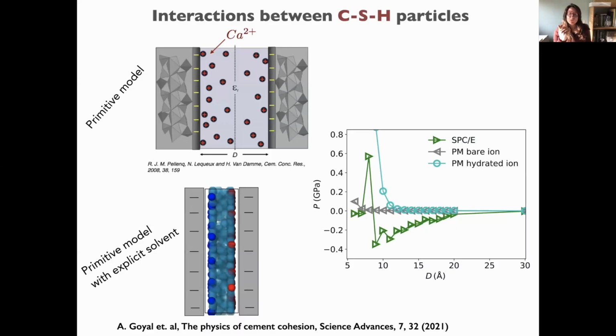So then if we move to the green curve, which corresponds to the primitive model with explicit solvent, and we model the water with the SPC model, we see that we have an attraction in the interaction between these two charged surfaces.